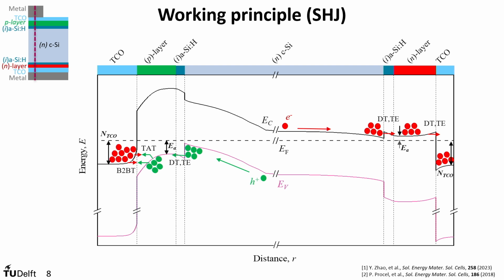Essentially, we look at the activation energy of the doped layers as well as the carrier concentration in the TCOs as two tuning knobs, for which we can have the best possible transport of majority carriers at these two sides of the wafer. And of course, the most interesting side is the P-type, because we also have possibilities for electrons to go across this barrier over here. So it is very important to tune especially the P-type layer in order to have the best possible transport in this type of devices.